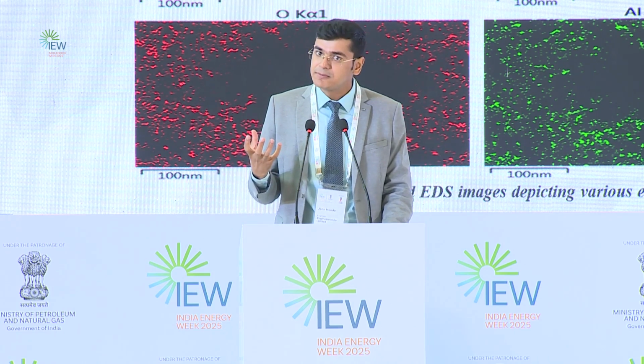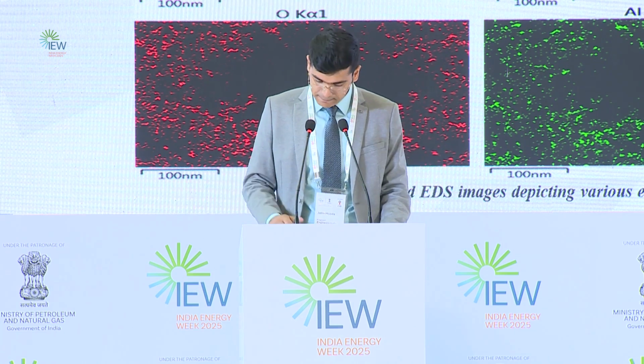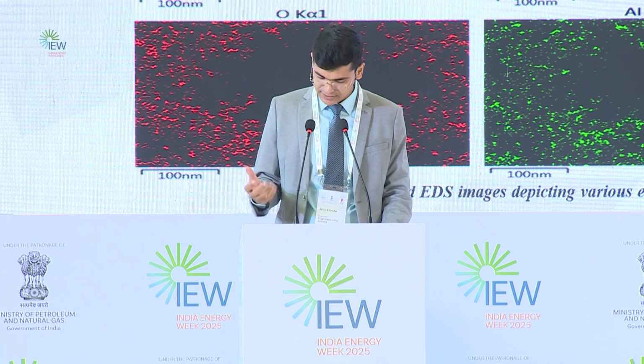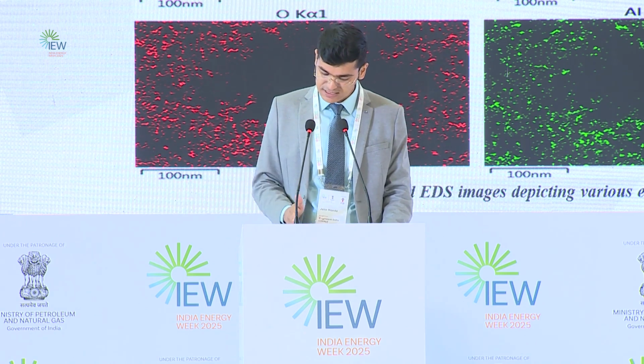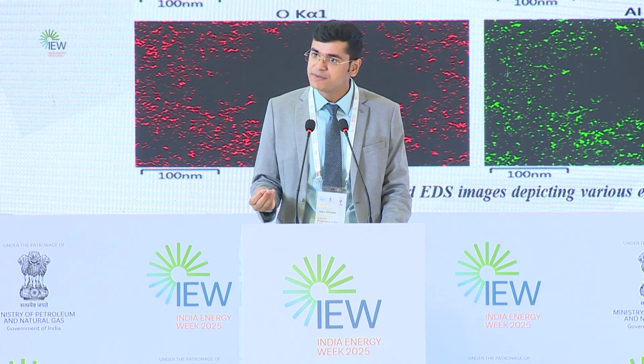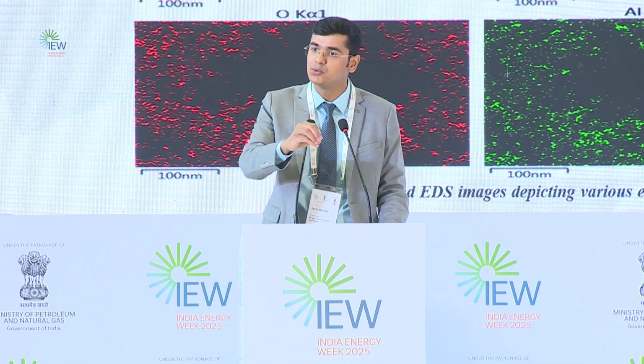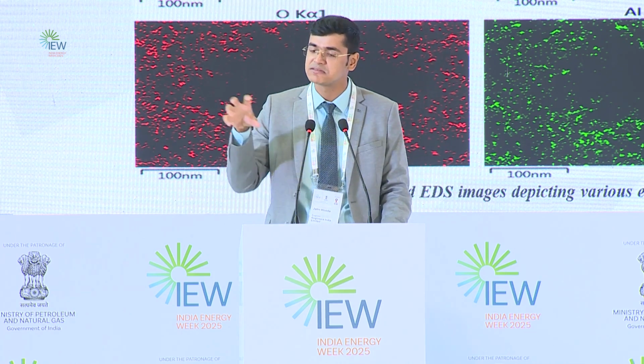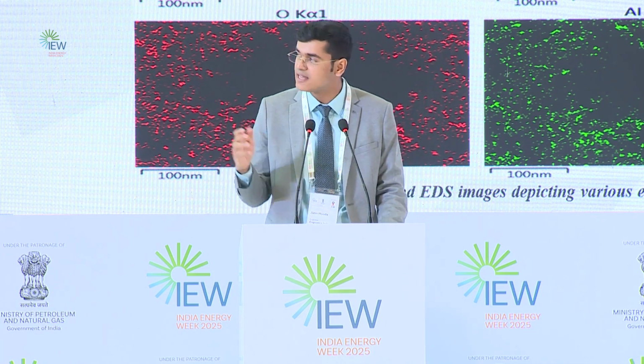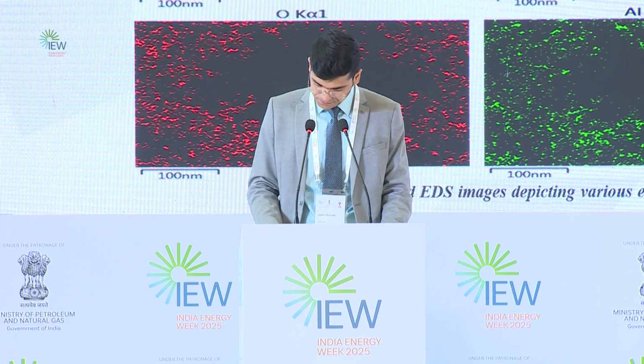Acquiring elemental maps, we can get through this method, and spot chemical analysis we can do. Discrimination of phases based on mean atomic numbers. It can categorize that this is O2, this is oxygen, this is calcium, this is silica. So we can get a spread as demonstrated in the image.